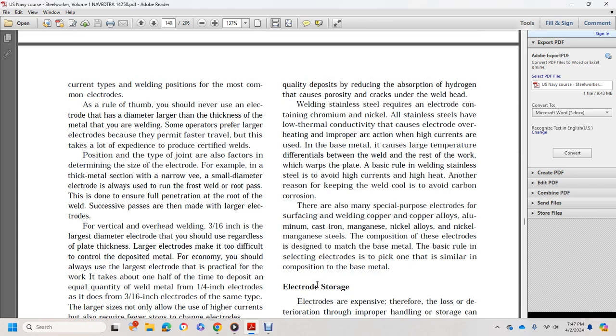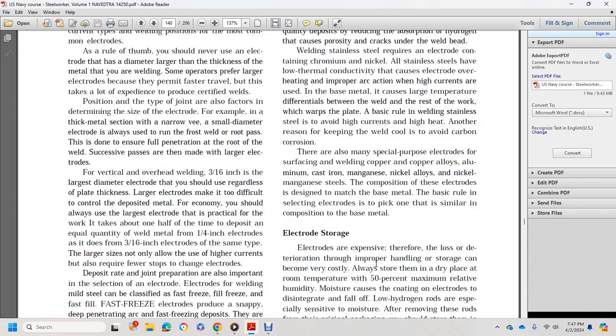Welding stainless steel requires an electrode containing chromium and nickel. All stainless steels have low thermal conductivity, which causes electrode overheating and improper arc action. High currents are used on base metal, causing a large temperature differential between the weld and the rest of the work, which warps the plate. When welding stainless steel, avoid high currents and high heat. Another reason for keeping the weld cool is to avoid carbon corrosion. There are also many special purpose electrodes for welding copper alloys, aluminum, cast iron, magnesium, nickel alloys, and manganese steel. Compositions are designed to match much of the base metal, but the basic rule of selecting electrodes is to pick one similar in composition to the base metal.